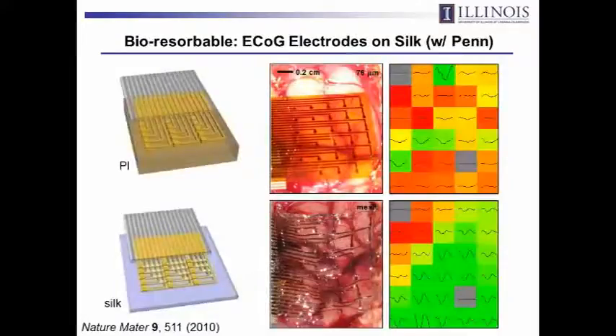The other way that you could think about using a bio-resorbable system is to combine it with something that's non-resorbable, like I showed you before, but for a specific purpose. So, for example, here's a thin open mesh array of electrodes. You'd like to integrate that with the brain. The brain is highly curved and textured, so you want that array of electrodes to be as conformal and floppy as possible. But when it's floppy enough to conform to the brain, it's no longer rigid enough to handle. So you can imagine using a temporary sheet of silk just to provide a way to mechanically manipulate this electrode array and mount it on the brain, where you would then dissolve the silk away, leaving just the mesh electrodes that could drop down into contact with that textured surface of the brain. So this would be an example of utility in something that's partially resorbable, but again, not quite the grander vision that I outlined previously.